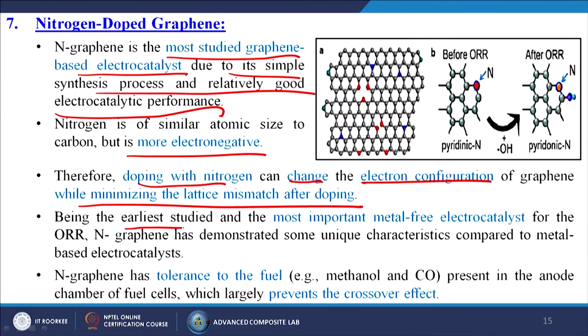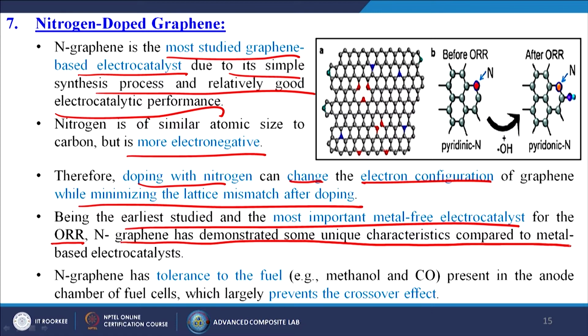Being the earliest studied and the most important metal free electrocatalyst for the ORR, N-graphene has demonstrated some unique characteristics compared to metal based electrocatalysts. N-graphene has tolerance to fuels like methanol and carbon monoxide present in the anode chamber of fuel cells, which largely prevents the crossover effects, because these kinds of gases are generated which can react with the electrode, but in this particular case N-graphene does not have any good reactions with the methanol or the carbon monoxide. That is why N doped graphene can sustain for a longer time as an electrocatalyst material.